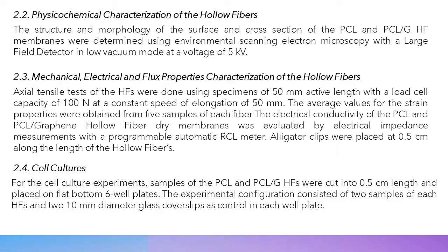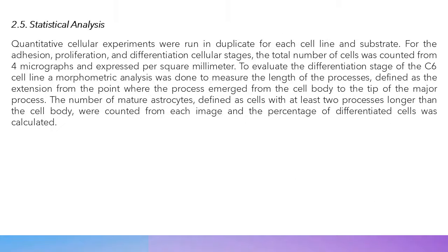Cell cultures. For the cell culture experiment, samples of PCL and PCL graphene hollow fibers were cut into 0.5 centimeter lengths and placed on the flat bottom of 6-well plates. The experimental configuration consists of 2 samples of each hollow fiber and two 10 millimeter diameter glass coverslips as control in each well plate. Last is the statistical analysis. Quantitative cellular experiments were run in duplicate for each cell line and substrate. For the adhesion, proliferation, and differentiation cellular stages, the total number of cells was counted from 4 micrographs and expressed per square millimeter.